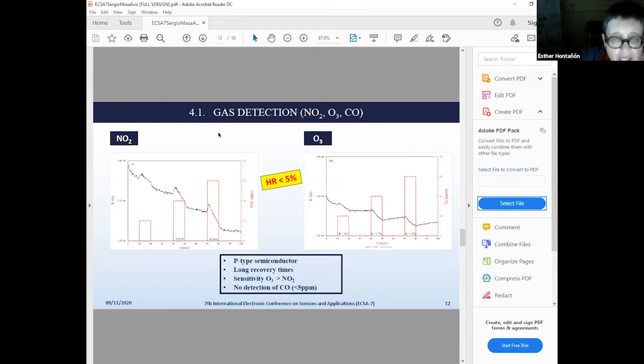In the case of the oxidizing gases, nitrogen dioxide and ozone, we observe that first the RGO behaves like a p-type semiconductor, because the resistance decreases when the gas is passing over the sensor, and the sensitivity is higher for ozone than for nitrogen dioxide. And the main point is that the recovery time is extremely long, for nitrogen dioxide even a bit worse than for ozone. Also, in this test we used dry air, where the gas mixture did not pass through the bubbler, but still you get a very low humidity level, let's say less than 5%.